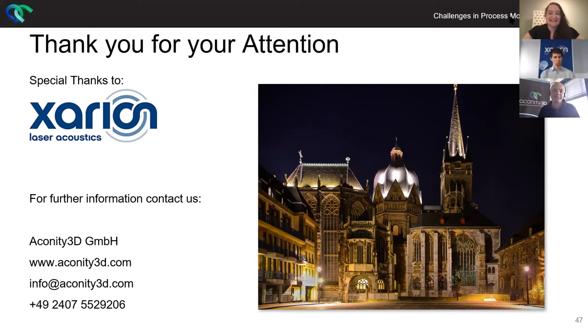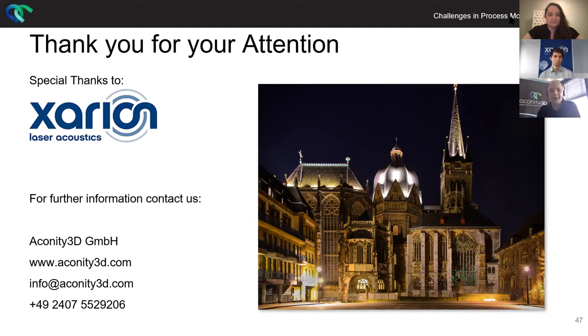Another anonymous attendee has asked: if I understood correctly, the OT camera is a line camera — how does it create a 2D image? Does it require an additional scanner? It was actually off-axis, placed with a certain region of interest. It's not a line camera — that was wrong information from my side, sorry. What's important to take away: it's a long exposure time. It's a special camera with 22 microns per pixel, so you have high resolution for long time exposure, which can be translated into a thermal emissivity or temperature if you know the emissivity.